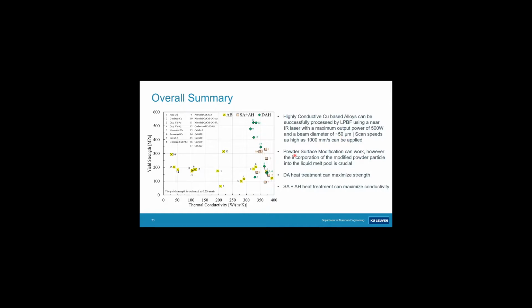With respect to powder surface modification, as I've shown, it can work, but there is more. It's not only the powder, it's also how the surface modified powder behaves whenever it enters the melt pool. And yeah, typically, if you want to maximize your strength, you go for a direct aging heat treatment. If you want to maximize conductivity, you solutionize first and you age harden. If you look for a combination, probably you will go for a DA heat treatment.